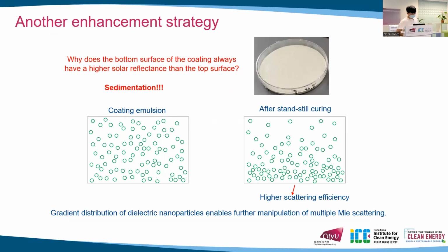And besides the fluorescence strategy, we also find another enhancement strategy that is inspired by a confusion from our experiment. We found that if we measure the solar reflectance of the coating, the bottom surface always has a higher solar reflectance than the top surface.